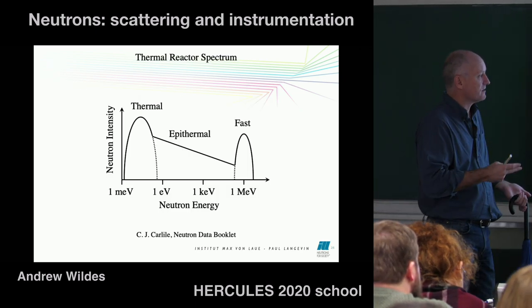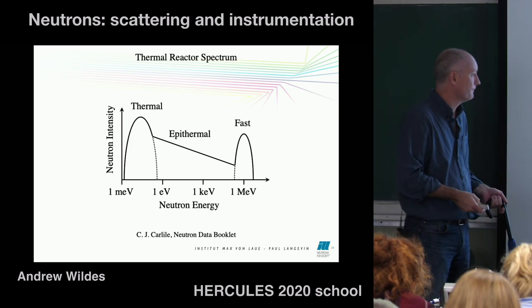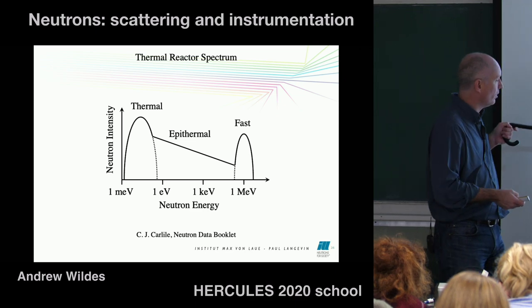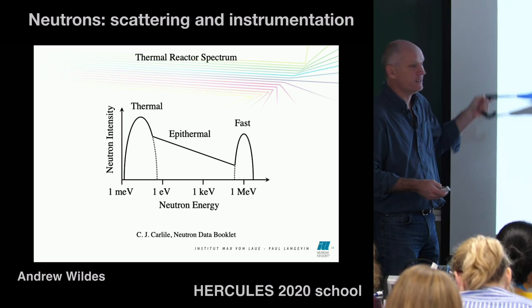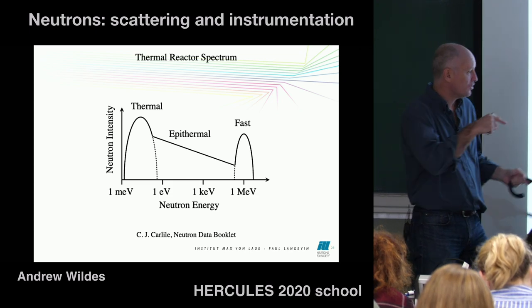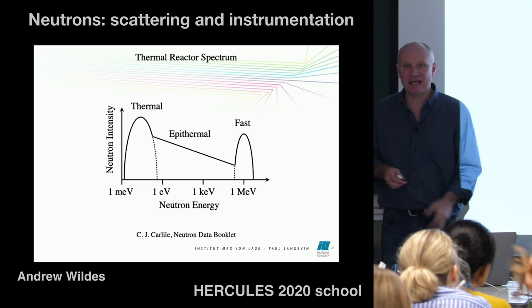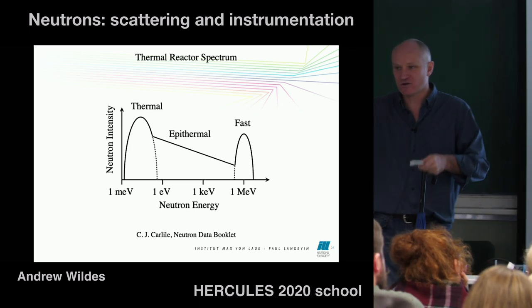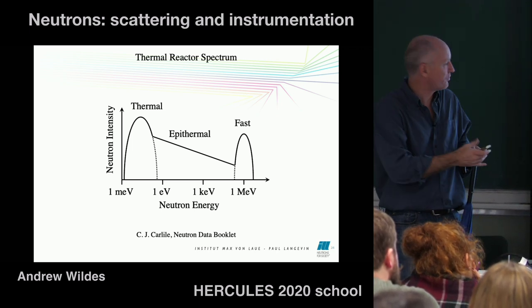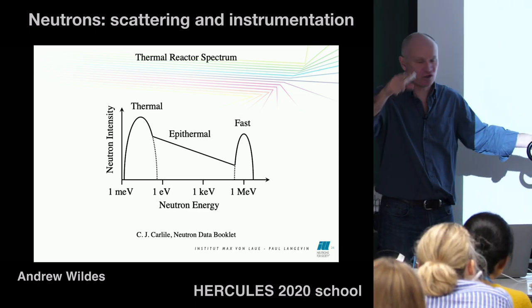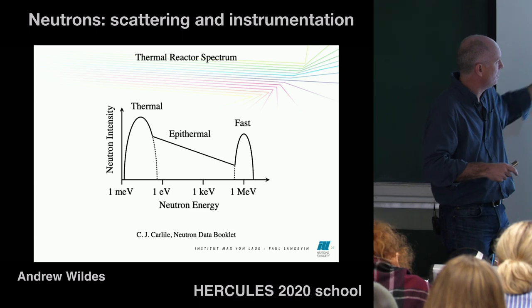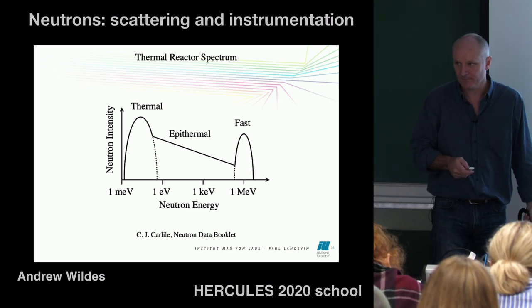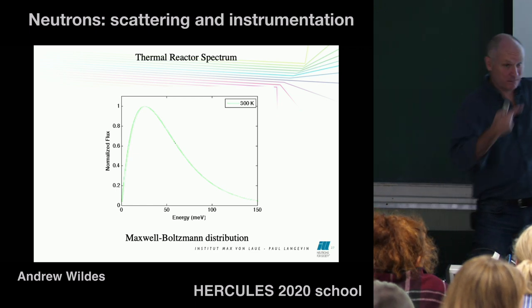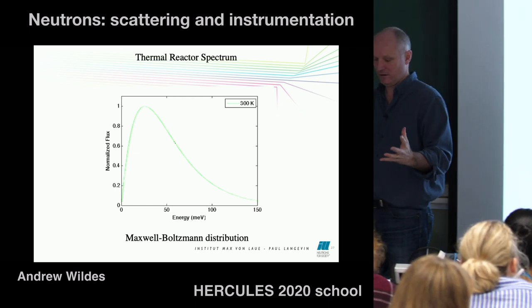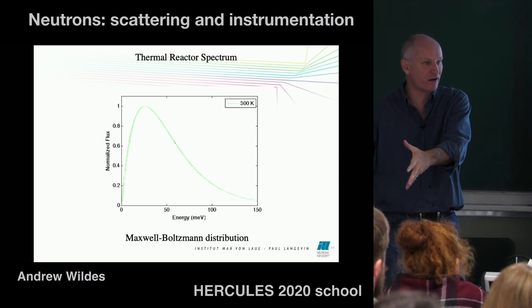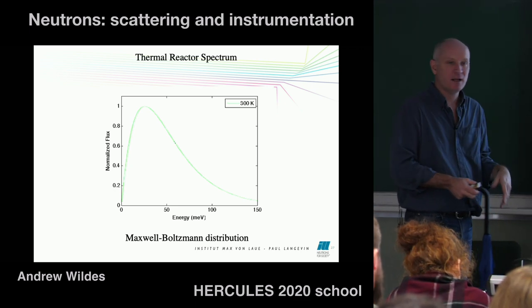So if you take a reactor, what we call a thermal reactor, like the ILL, then you can plot the neutron energy here versus the neutron intensity in a moderated reactor. So what you find is that there's this peak here in the mega electron volt regime, and that peak comes about, those are the neutrons that are initially released in the fission process. And then depending on how efficient the moderator is, you see this great big long tail, and then this peak here in what's called the thermal flux. Right? It's called thermal because at the ILL, the temperature of the liquid moderator, of the deuterated water, the heavy water moderator, is kept at about room temperature.